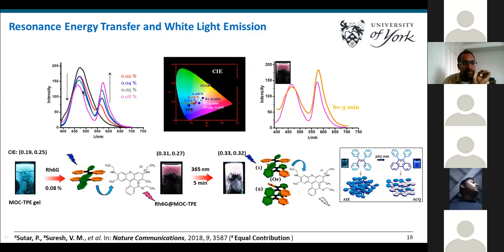We started to dope this particular gel with different rhodamine acceptors. As you see, when we increase the concentration of rhodamine 6G in the gel from 0.02 to 0.08%, we see a decrease in the emission from the TPE and a corresponding increase in the emission from the acceptor, which is at 560 nanometers. At 0.08%, we see a complete transformation of this cyan emitting gel to a pink light emitting gel, lying somewhere here in the region, which clearly says that the emission from the gel is pink. The CIE coordinates are 0.31 and 0.27.